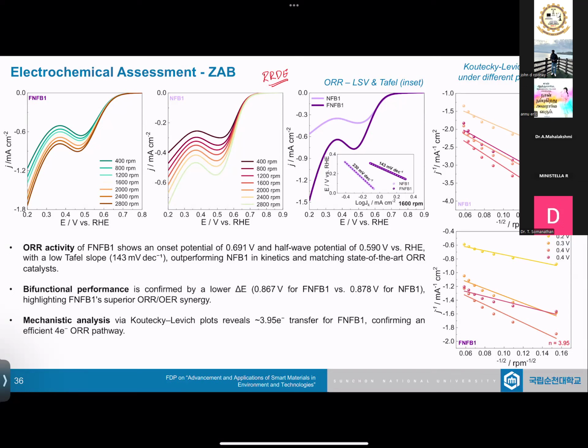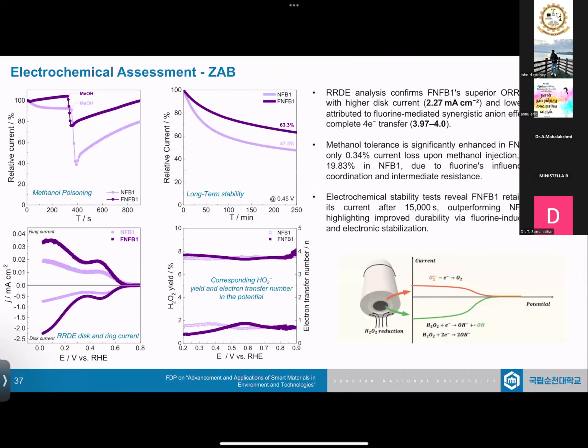Yes, it's bringing about the change in activity, which you can see over here with respect to the Tafel values that we got, whereas the number of electron transfer is still very good. It has to be 4, and it was perfect over here. We also extensively tested the material in methanol poisoning, long-term stability, RRDE-based testing, H2O2 yield, and everything. And we found out that fluorine is really supporting and enabling the system to work much better.